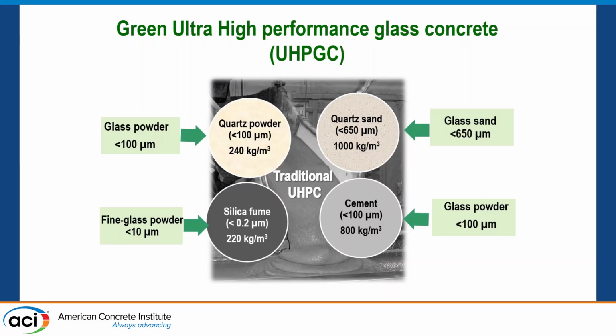So we started with the glass powder replacing completely the quartz powder. The quartz sand, we replaced a part of the quartz sand, a part of cement, and also, I don't present that here, but we ground the glass very, very fine to around 2 or 3 micron, and we use it in replacement of a part of silica fume.